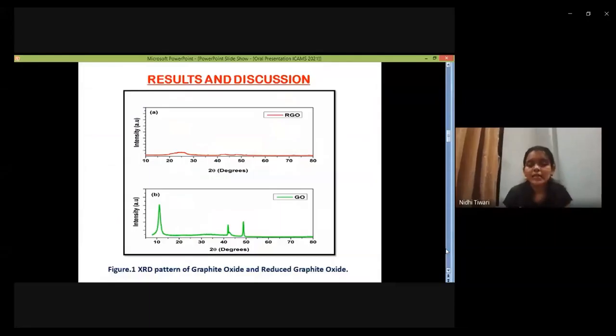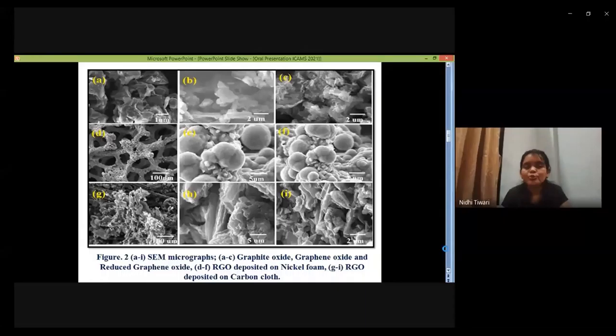Moving on to results and discussion. In the XRD pattern, we can see that the 10 degree peak of graphite oxide is not present in the RGO XRD pattern. And also the d-spacing has increased, which proves that GO has been separated into layers, in the form of reduced graphene oxide. Moving on to SEM studies, from morphological studies, we can see different phases of graphite oxide, then graphene oxide, then reduced graphene oxide. The next series shows the deposition of RGO on nickel foam.